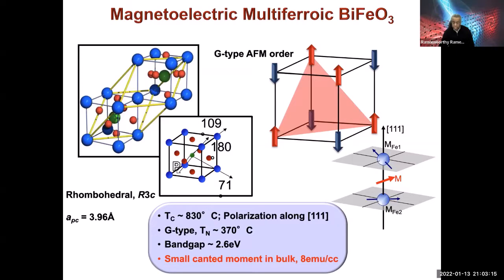Ab initio folks did clarify. We did a lot of other measurements. The reason was in the past, in the 60s and 70s, people were not able to make high quality materials. And with epitaxial synthesis, we were able to do that. Now, the magnetism here was really complicated. I'm not going to go into the huge drama that happened on the magnetism side, but this material has G-type antiferromagnetism, which you can see here. You have 111 sheets, which are ferromagnetic in plane, antiferromagnetic out of plane, like you see here.